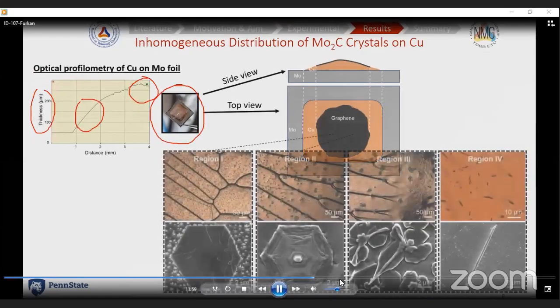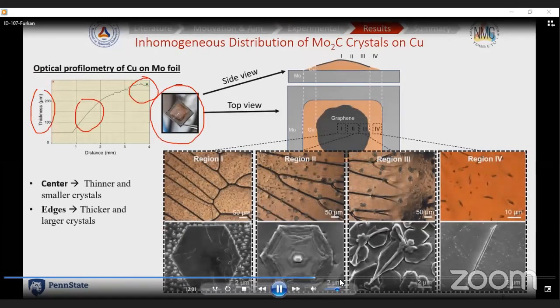So what we observed is that at the center region we observed thinner and also hexagonal crystals with smaller size compared to the ones at the edge region. Here, as you see, the crystal size gets larger when we go from center to the edge, and also their morphology is dendritic or flower-like shape.